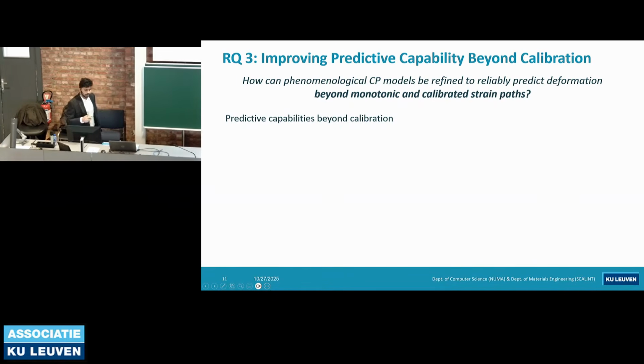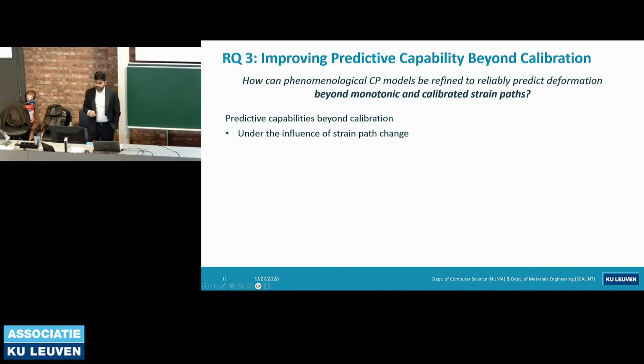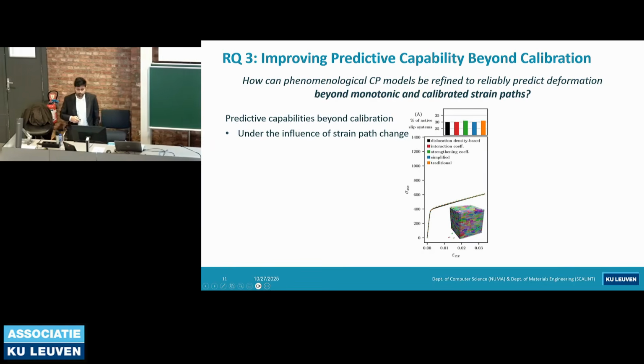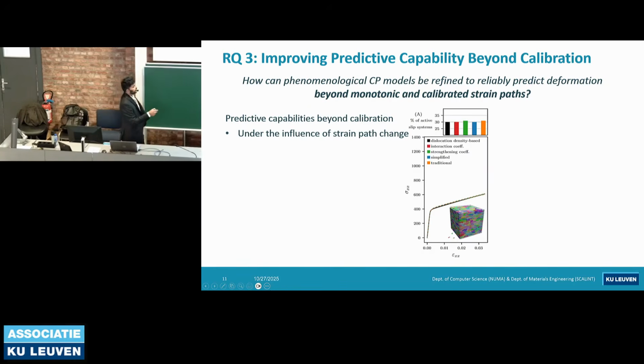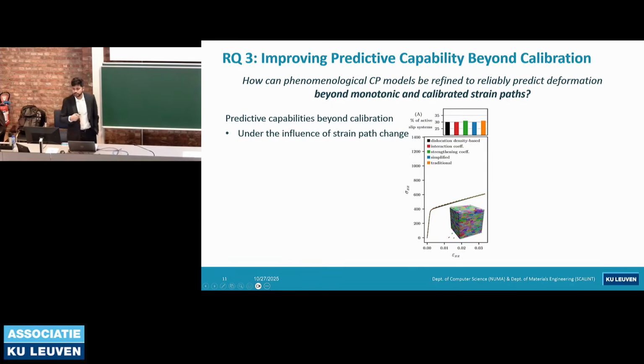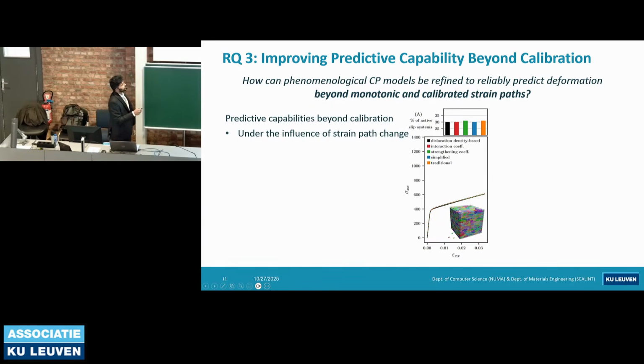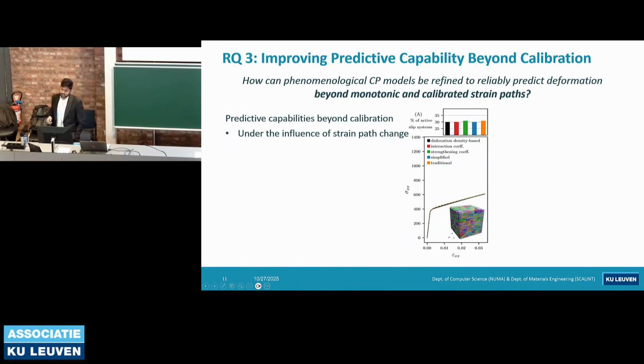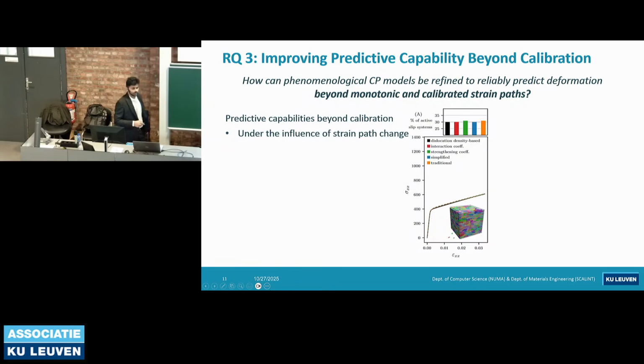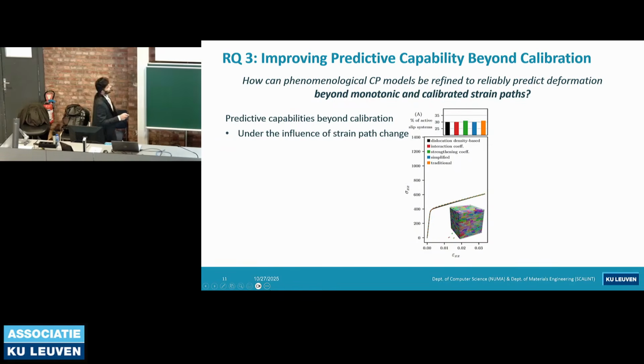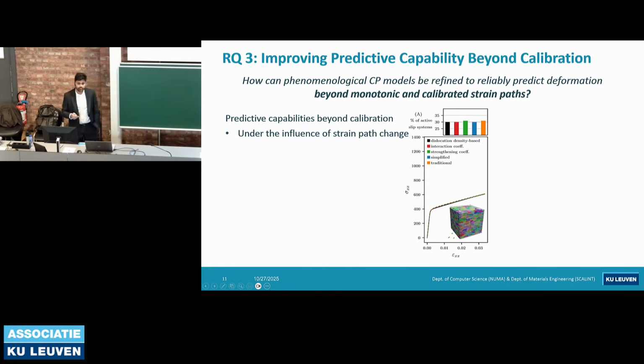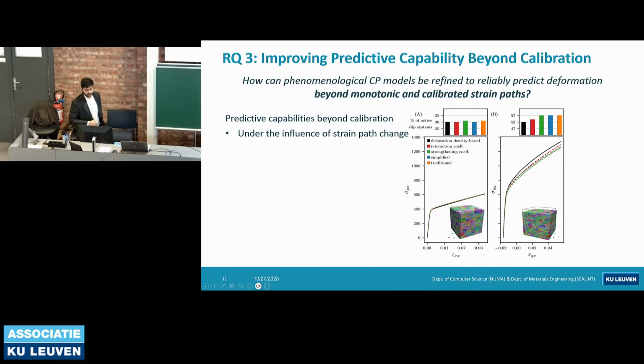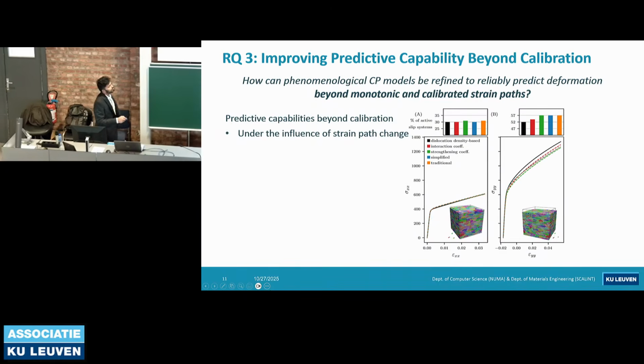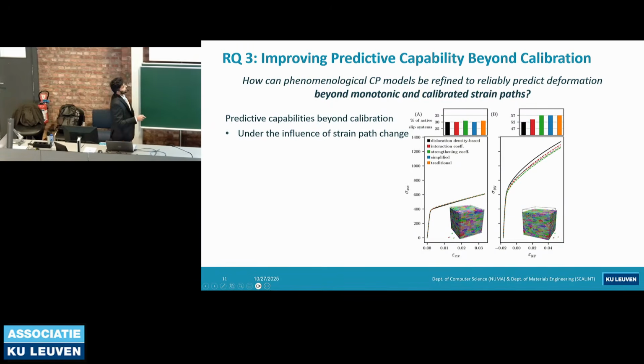Now, predictive capabilities beyond the domain of calibration. For that, we had to inflict a strain path change. We did that first by having a monotonic load. Here, since this was calibrated, this is macroscopic stress versus strain. Since this is a monotonic load, only 30% of the slip systems in the volume are activated. As the wise man Taylor once said, you don't need all the slip systems to accommodate a deformation, but only 4 or 5 of them. So here, as you can see, all lines lie on each other, and this is expected as this is a monotonic load. And then we inflict a strain path change by loading it in the transverse direction. And here, you can see that it hardens or yields at a higher level because of initial hardening.